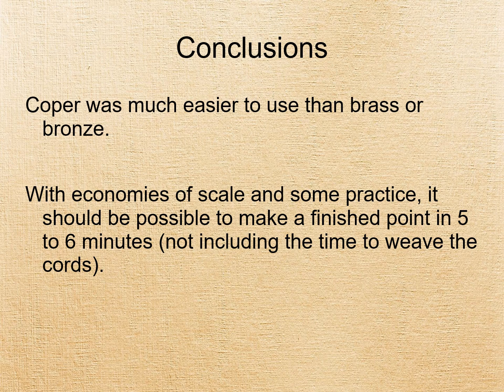I believe that with practice, this time for assembling a finished point can be reduced to less than 4 minutes total. Add in the time to source and produce the thin metal sheets needed for type 2 and type 3 aiglets, and I feel that with economies of scale, it might be possible to create a single point within 5 to 6 minutes. This is within the time frame that I feel is acceptable for the mass production of these ubiquitous items of everyday clothing during the early medieval, medieval, and post-medieval eras.